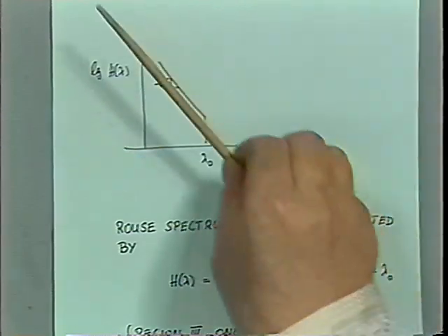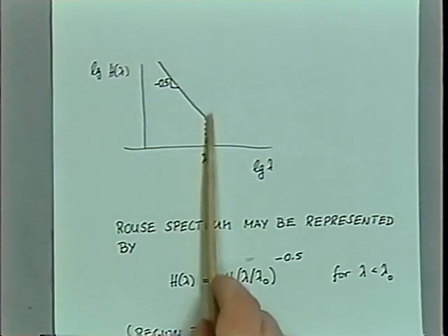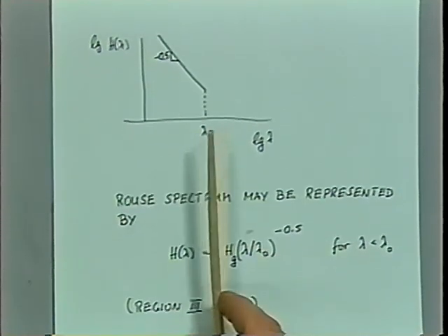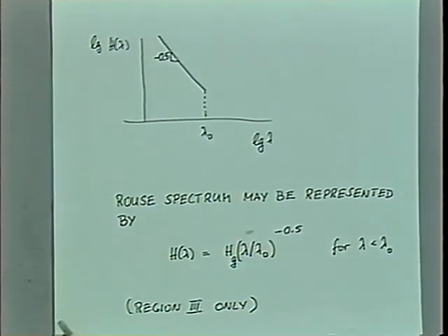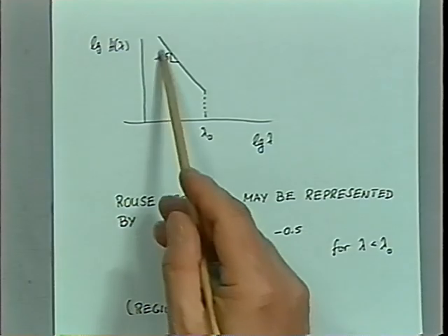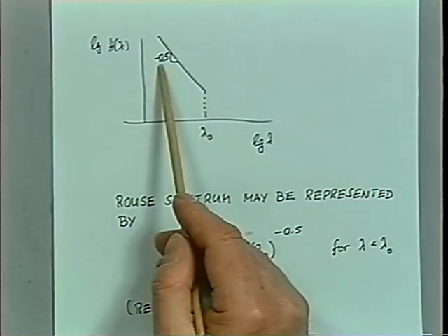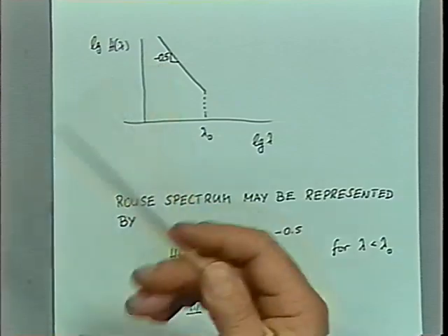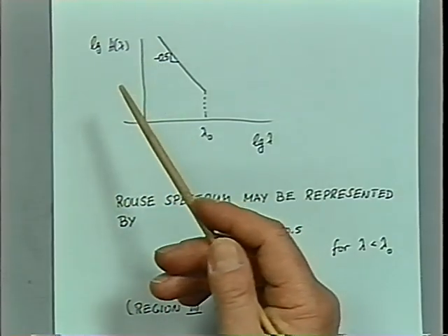Remember, the entanglement regime would come in like this. It's just the glass, and it's cut off at its longest time. We're talking about a molecule which is at its entanglement molecular weight, but it's not longer. It's not able to form entanglements. And when you take this spectrum, of course with a slope of minus 0.5 because of the 1/2 exponent in the Rouse model, if there would be another exponent, you could take another slope.